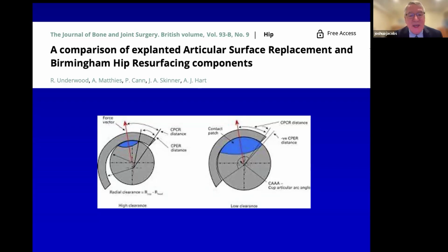So this contact patch to rim distance, if it was within the contact area and not within the edge of the component, it turned out that that dictated the performance of the device. Now, as you can see, that can be related to the hemisphericity of the acetabular component. It can be related to the clearance, which is the difference of the radius between the socket and the head, and also related to factors involved in lubrication and how the implant is inserted.